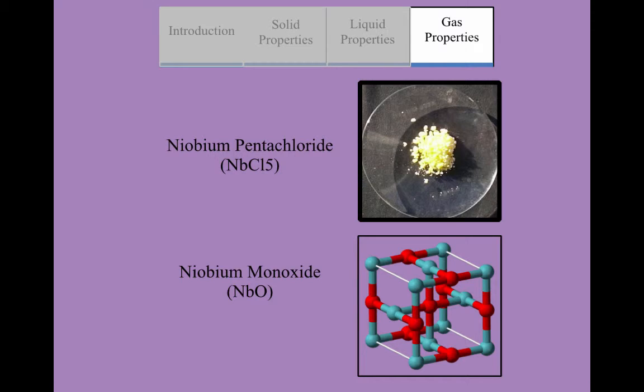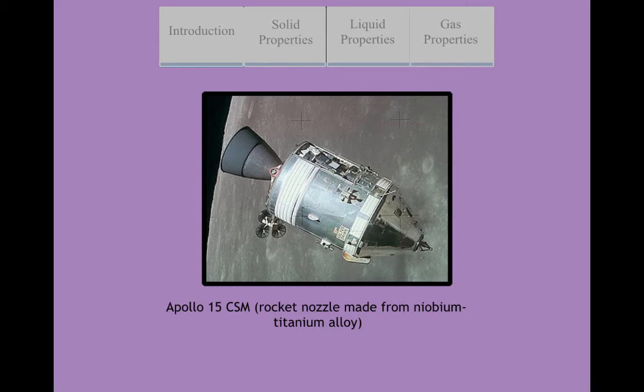Niobium most readily reacts with non-metals at high temperatures and begins to oxidize in air at 200 degrees Celsius. Niobium will form oxides and halides and in most compounds will be found in the plus-5 oxidation state.